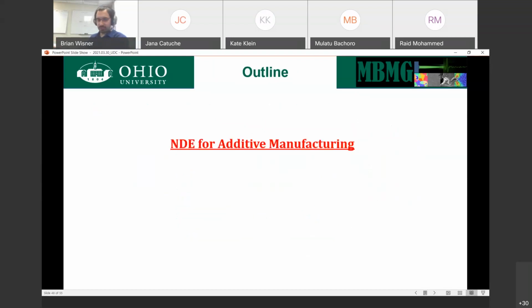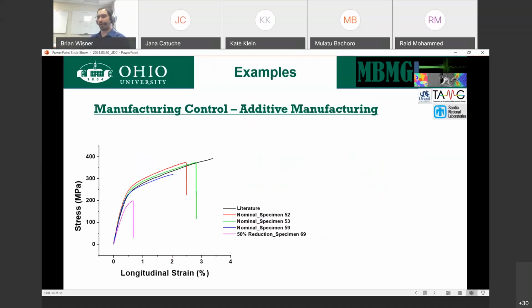Now, the one I spend most of my life on, NDE for additive manufacturing. I mentioned before I went through a detail of that aluminum material, and I did it for this reason. We were trying to understand additive parameters and how the material responds. So we call this nominal, 50% reduced, and you'll see there's also a 25% reduced. Nominal is what literature proposes as the optimum manufacturing parameters for aluminum, silicon 10, magnesium. 50% reduction in power means we took the laser power and we just cut it in half. And we wanted to see what would happen.